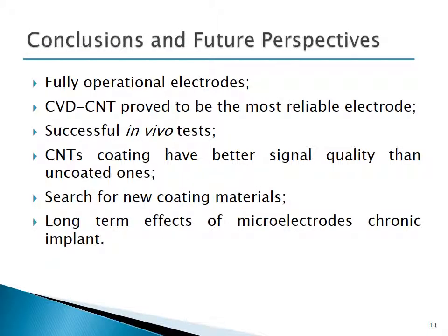Now, we obtain three fully operational electrodes with different coatings. Carbon nanotubes formed by CVD proved to be the most reliable electrodes. However, all of them were successful in in vivo tests. Carbon nanotube coatings have better signal quality than uncoated ones, and this is a very good thing to use in the future to study the brain.